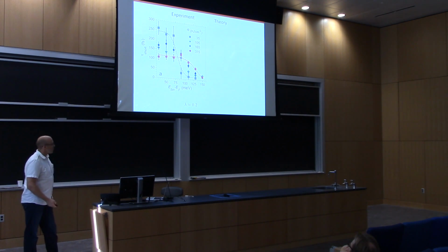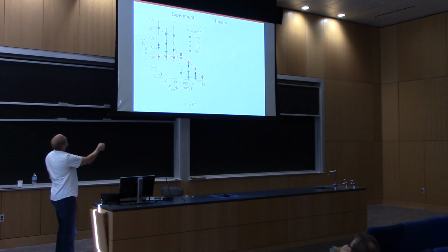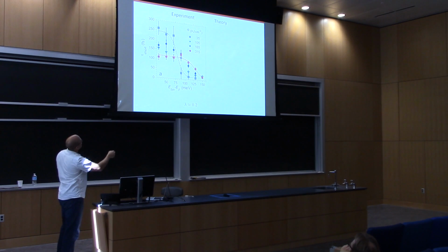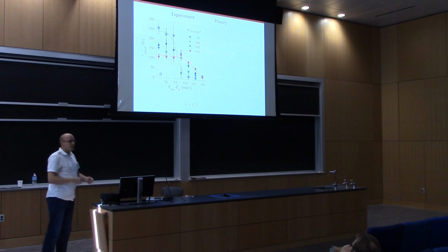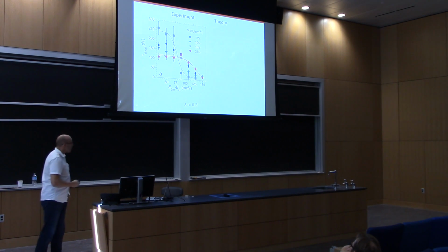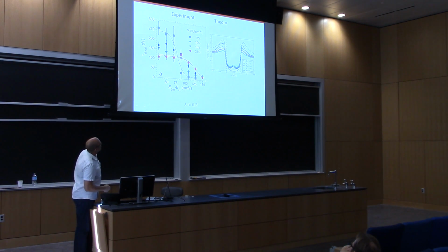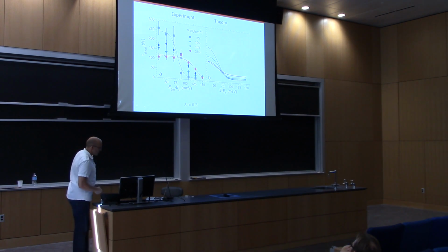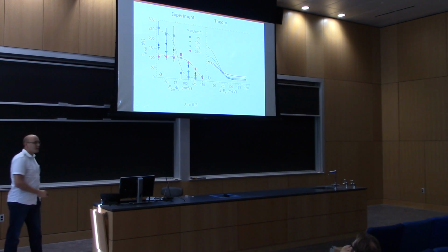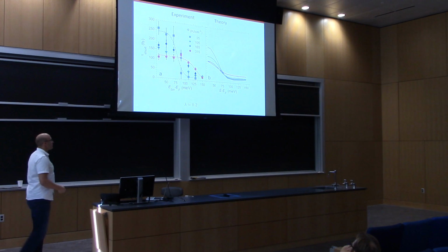We can go a bit further, we can do some analysis. Here's tau from the experiments as a function of energy and fluence. You see this step at low fluence, and that step sort of softens at high fluence. This is a theory picture, or really the upside down version of that. And we actually get a reasonably good agreement.